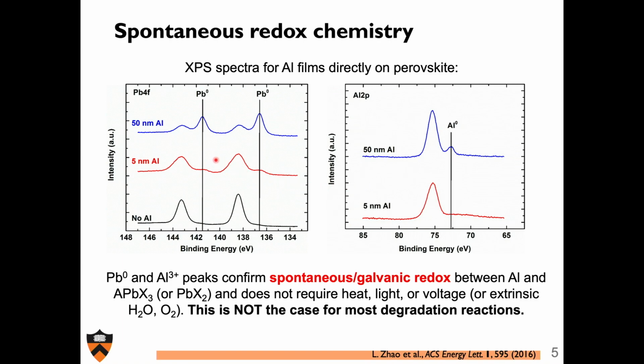And so if you have an easily oxidized and strongly reductive metal like aluminum, instead of staying as pristine aluminum 0, what will happen is you'll have a metal-metal cation redox reaction with lead 2, and you will generate a lot of lead 0, and you'll generate a lot of aluminum 3 in the process, because aluminum 3 has a stronger electrochemical potential than lead 2 to lead 0. And so that's the end consequence. This is a very obvious one. This is a spontaneous one.